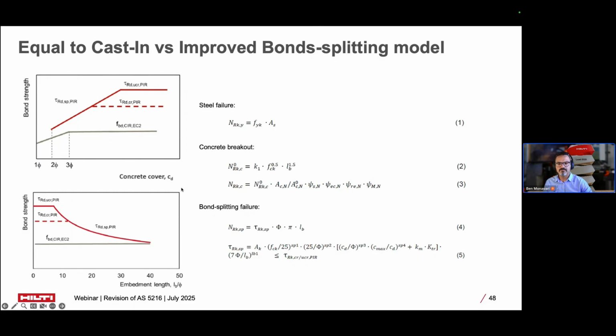So previously, for example, for RE500V4, for a specific size, we used to say it has 10 MPa, 2.5 MPa, or a constant value. But as you can see here, we have a new equation. So the bond strength is not a constant value anymore. It depends on the embeddment depth. It also depends on the concrete cover. We have to calculate how much capacity we have in different depth. So it's a very hard calculation if we want to do by hand, but obviously with engineering software, we can do it automatically with ease. Okay.